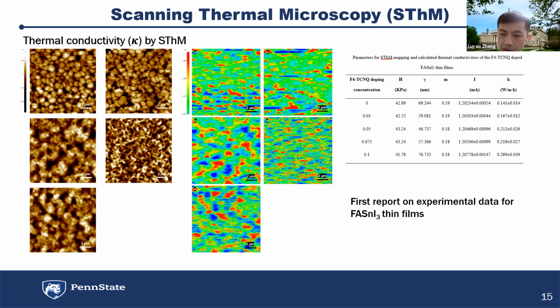And we found that this FA tin iodide exhibits even lower thermal conductivity compared to some lead-based or cesium tin iodide, as shown here. It's only about 0.2. This is a pretty good value for tin materials. And also, this is the first report of experimental data for FA tin iodide thin films.